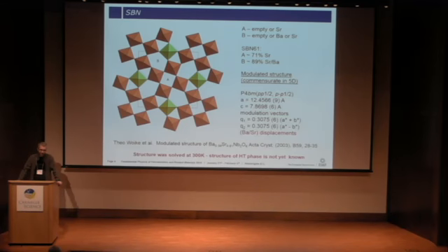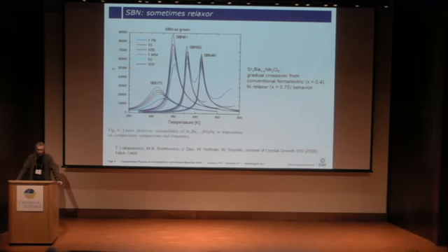Well, the structure was solved only at ambient conditions in the polar phase. What happens in the non-polar phase above the transition, nobody knows. Once again, it's sometimes a relaxor. If you go through the compositions, it can be a well-defined relaxor for, say, 75%, or it could appear like a normal ferroelectric, like for 40%. The composition we started with was 60%, or around something which you grow from a congruent melt.